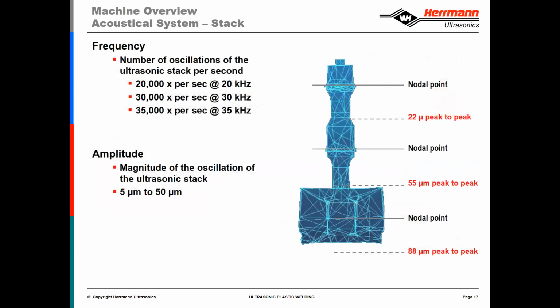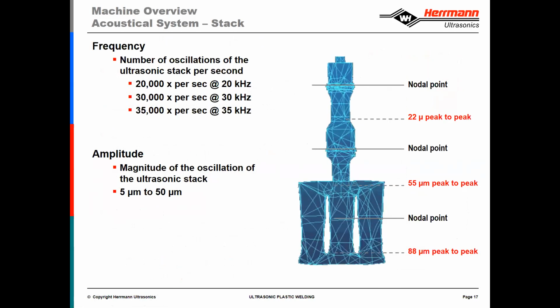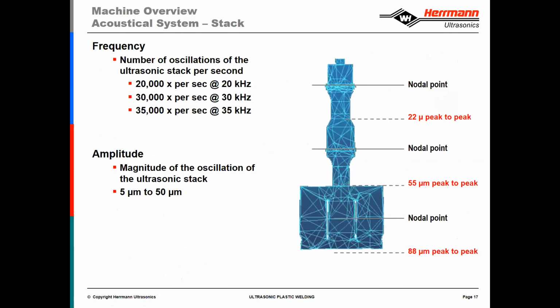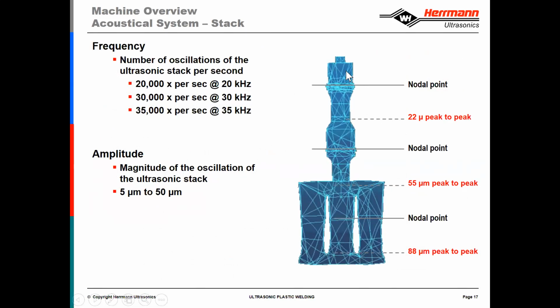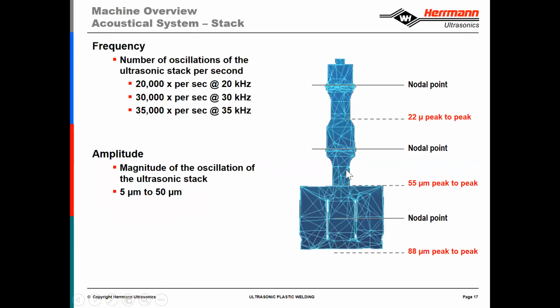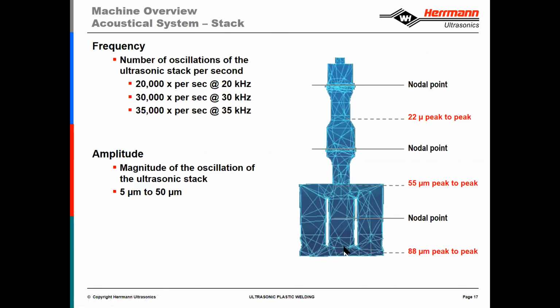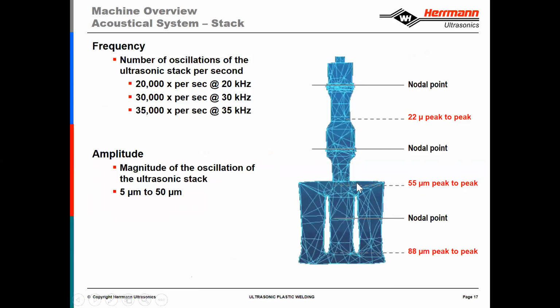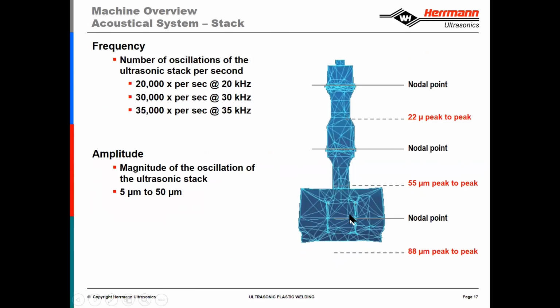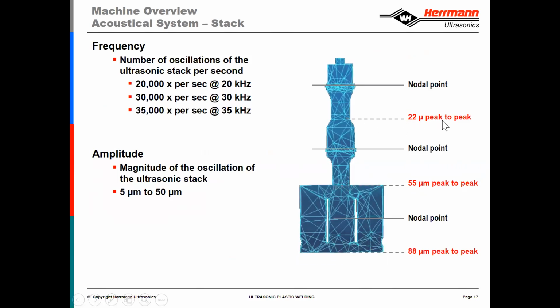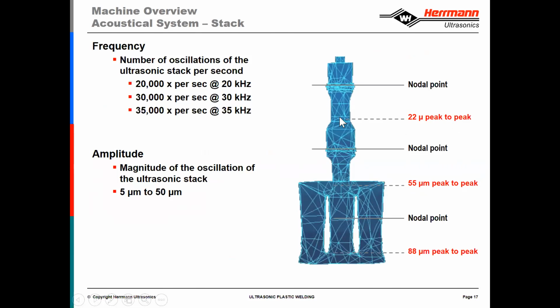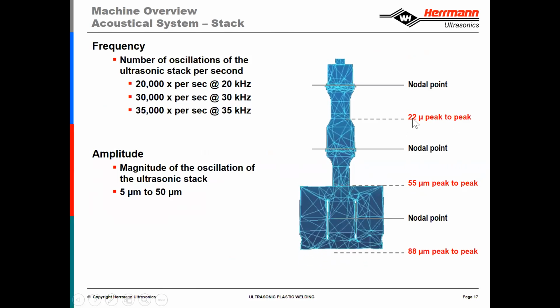This graphical representation is using our finite element analysis, or our modeling. Obviously, it's greatly slowed down and greatly exaggerated, but you can see this longitudinal vibration. The direction of propagation is up and down. This micro jackhammering that we need is like clapping your hands together, not scrubbing your hands together. We can see the nodal points. In this case, we're measuring peak to peak, and the output of the converter is 10.5 microns, or 21 to 22 peak to peak.